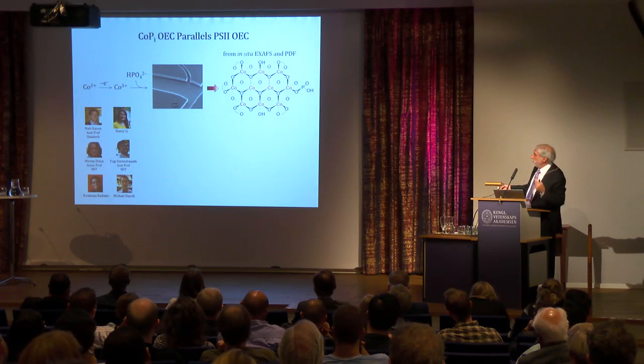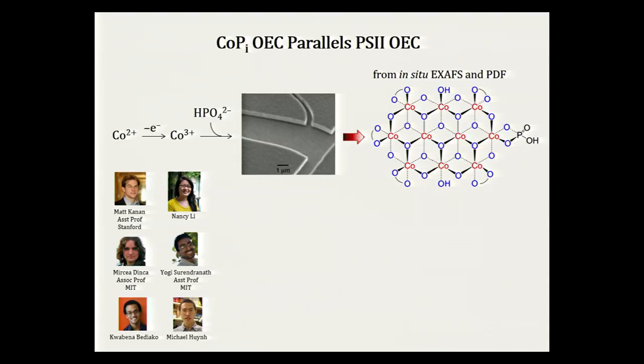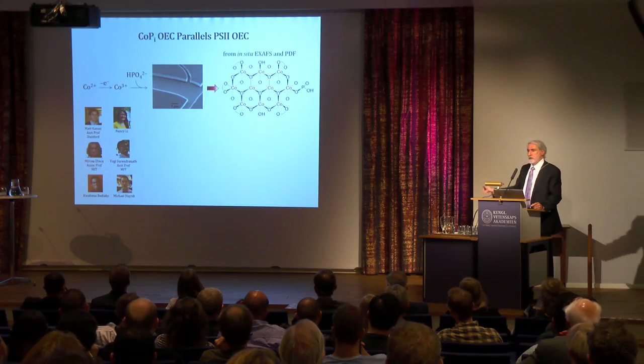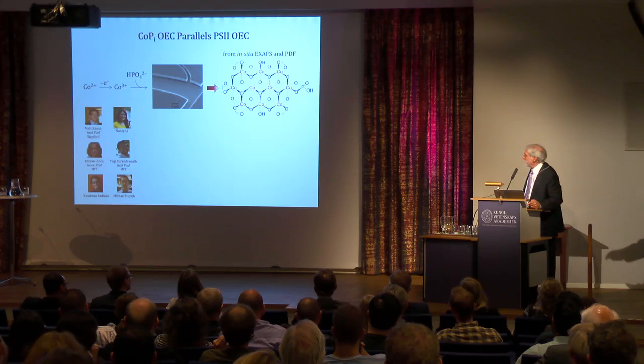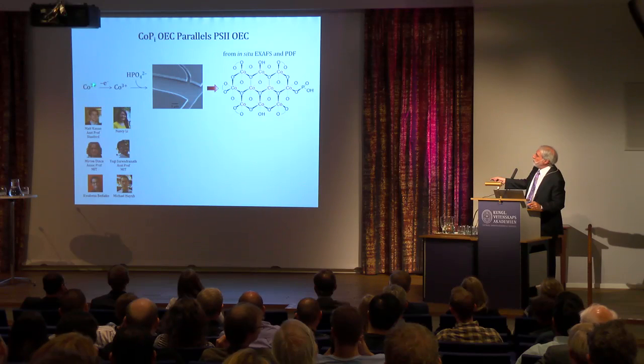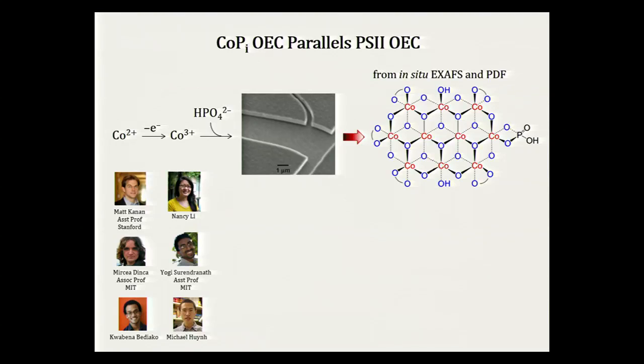And Matt Kanan, and this is 2008, showed you could oxidize cobalt-2 to cobalt-3. So cobalt is, if this is the periodic table, cobalt's right here. It's on the right side of the periodic table in the transition metal series. And so when you oxidize cobalt, take one electron from cobalt in solution, you make cobalt-3. In the presence of phosphate, you get a thin film on the electrode. And we did a lot of experiments. We could go to do synchrotron radiation at Stanford, and we could shine high-energy synchrotron radiation as the catalysis was going on, and we could figure out the structure.